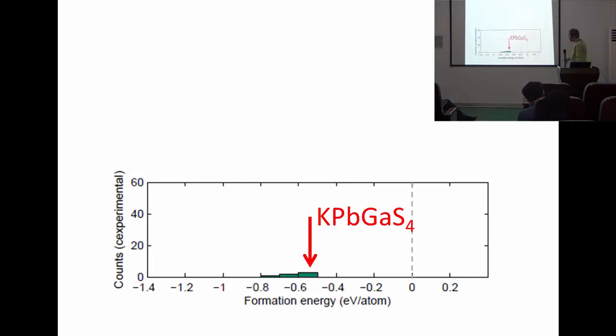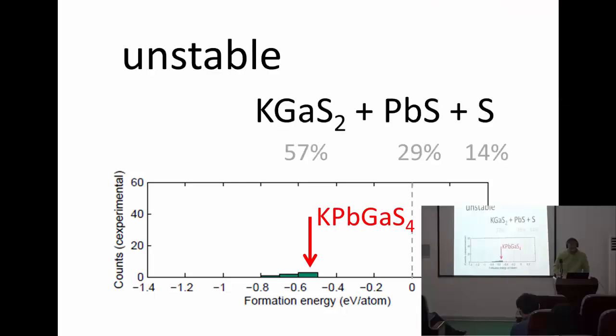I take another one that is not experimentally known, or perhaps not yet experimentally known, I don't know. So potassium, lead, gallium, sulfur 4. And if we do here the same story, then we find that this one is unstable. If you take the ternary crystal with potassium, gallium, sulfur 2, the binary crystal, lead sulfide, and the elemental crystal with just sulfur, then this combination has a lower energy than this quaternary crystal. So the chances that someone ever will find that particular one are very small.